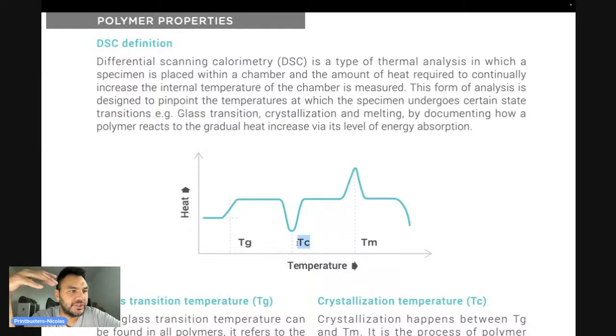So the crystal can form at pretty much any temperature, more or less. But if it's too cold, okay, here's how you can picture it. You can see it like this for the crystallization temperature. All the polymers have some type of energy, right? And the higher the temperature, the more energy they have. So the more energy, the faster they can move. If the temperature is not too high, they can move, and they are going to slowly form all the crystals, right? If you give more temperature, then they are going to form the crystal faster because they have more energy.